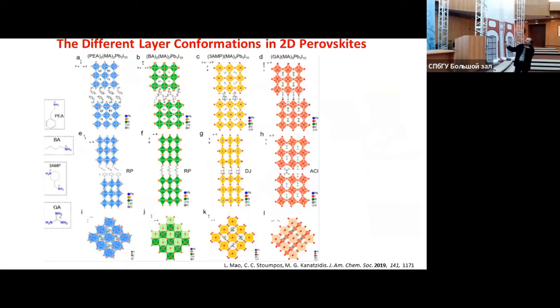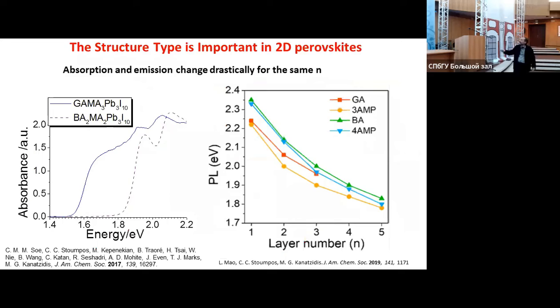And this is how this conformation would look like, and why we care. Because for a given set of layers, this change in the three types of perovskite can give significantly different properties in the sequence as you build the layers. And the origin, potentially, can be the energy difference associated with communication, electronic communication between the layers. Again, there is no definitive proof about that, but we have experimental data that we understand that there is actually a difference in the energy level,